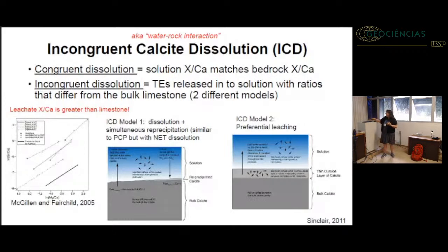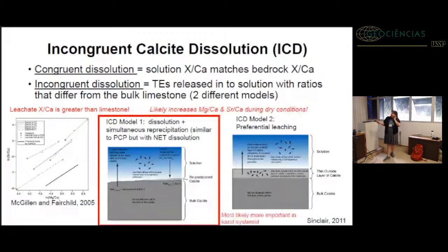In this particular 2011 paper, it's argued that this model 1 is most likely the one that is dominant in most karst settings and able to cause bigger changes, and that's effectively because this preferential leaching effect can only go a little bit far, and then the longer dissolution proceeds, the more congruent it becomes effectively.